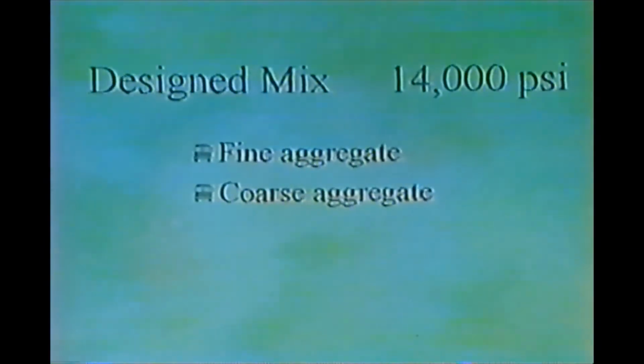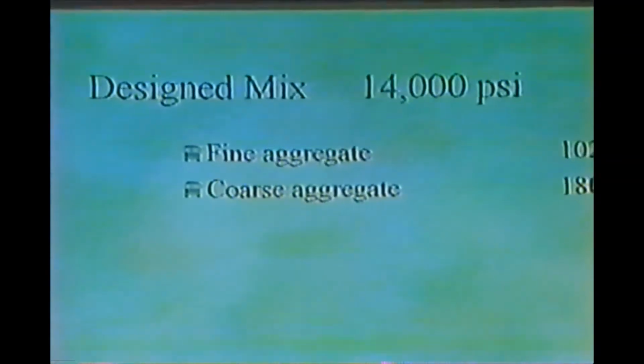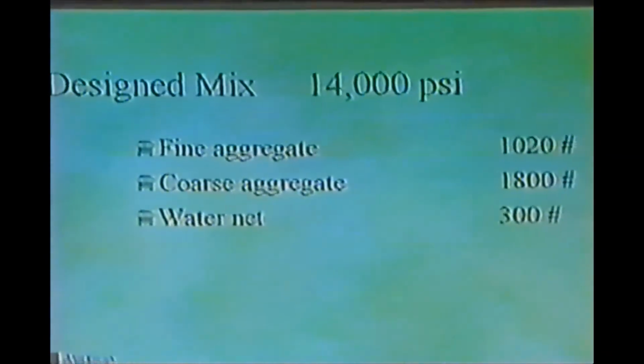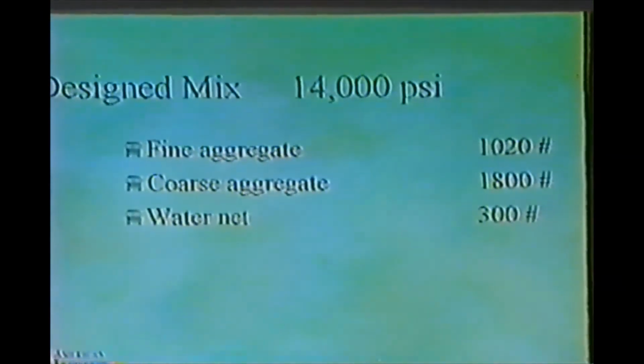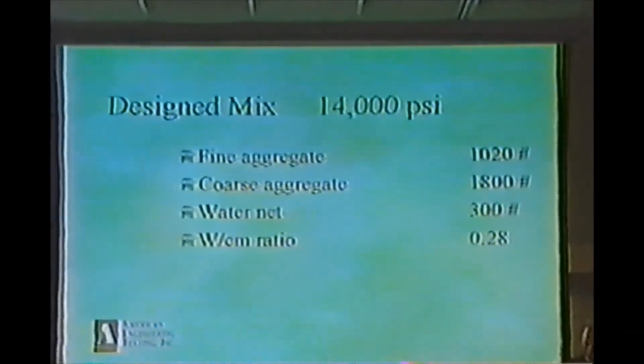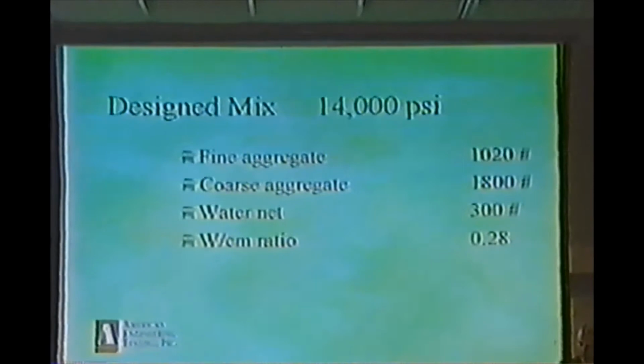So again, now we go to the aggregate side. Fine aggregate, 1,020 pounds. Coarse aggregate, 1,800 pounds. Water, 300 pounds or 35 gallons. Which gives us a water cement ratio of 0.28.